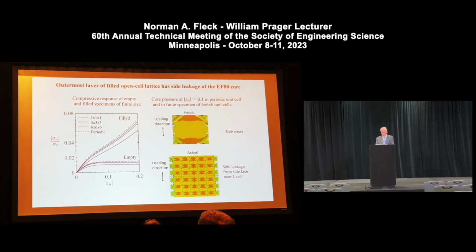One can ask the question, which has been asked many times in the case of an empty lattice, how big a specimen do you need in order to probe the material properties of the lattice, of the foam? And the answer is not many cells. So if we take a single unit cell and either do simulations or experiments, in this case it's simulations, a single cell has got a stress-strain curve in the empty state here and in the filled state here by the black line. As you make more and more cells and build them up and go to the infinite case of the periodic cell, you find that there's some elevation in response, but not very much.